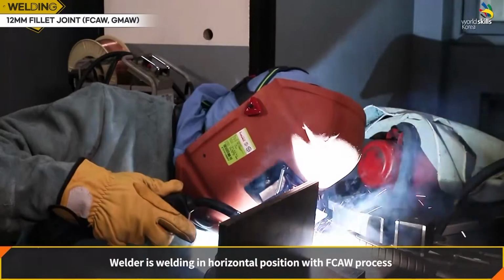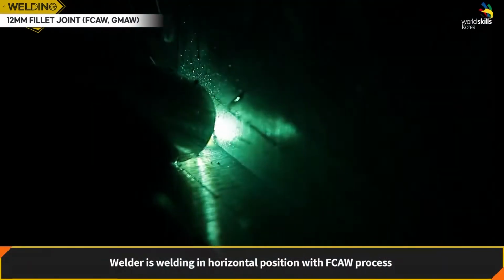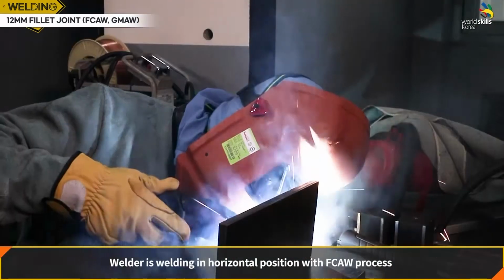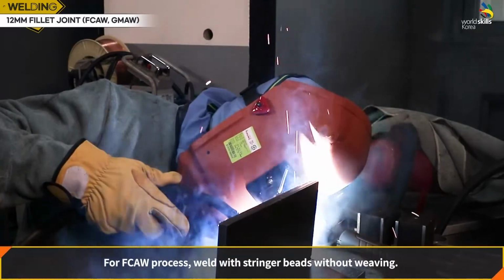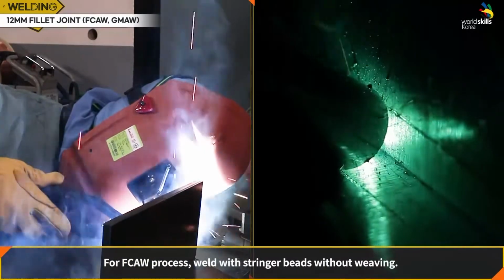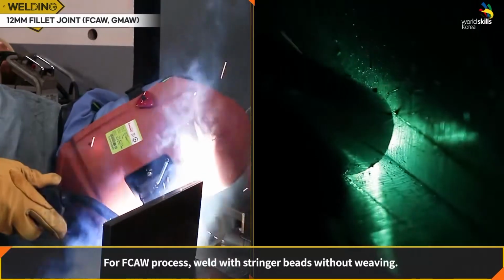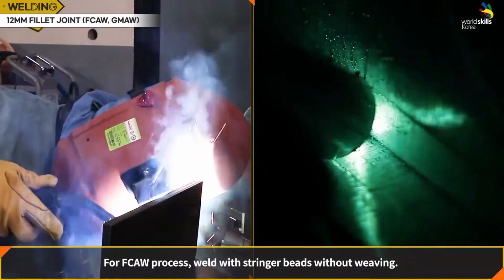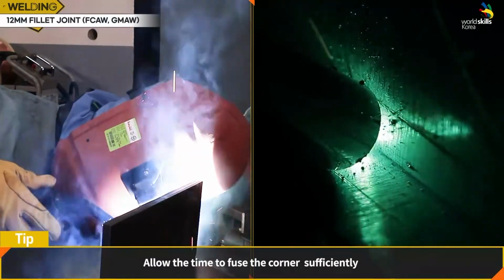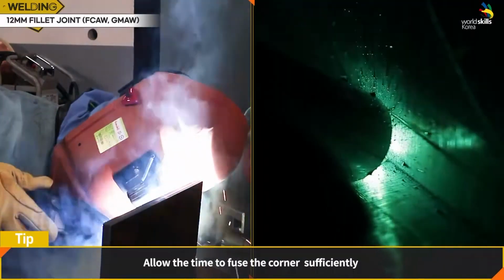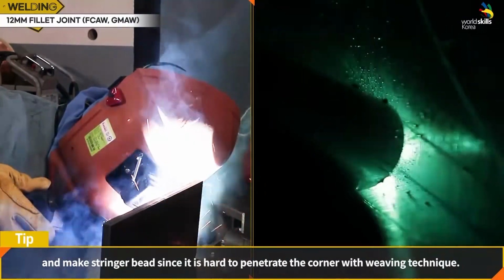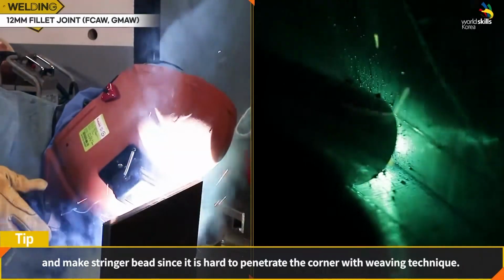The welder is welding in horizontal position with FCAW process. For FCAW process, weld with stringer beads without weaving. Allow time to fuse the corner sufficiently and make a stringer bead, since it is hard to penetrate the corner with weaving technique.